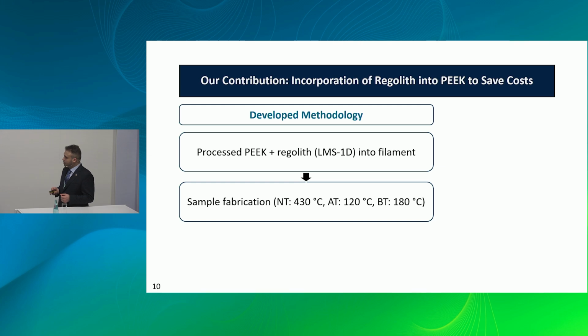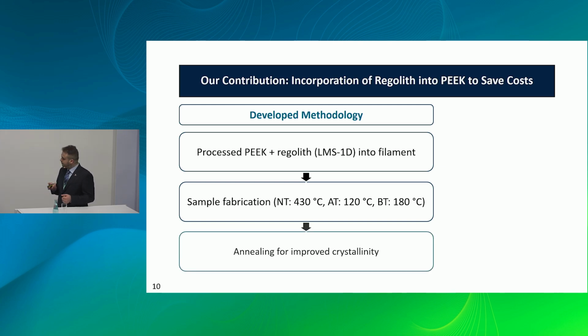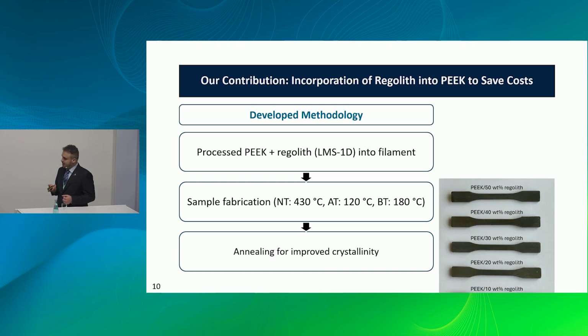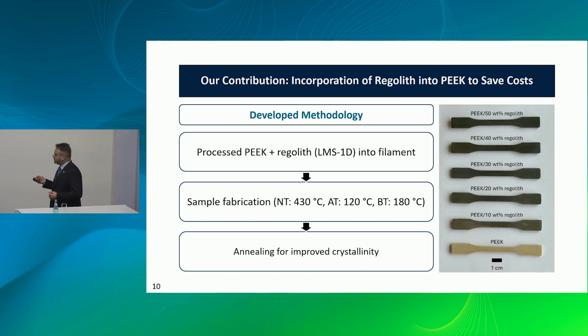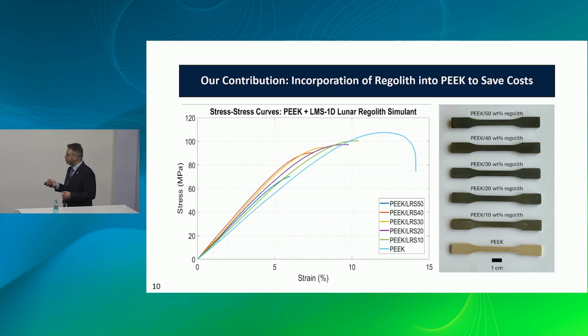The nozzle temperature is around 430 degrees. Ambient temperature is 120 degrees, and bed temperature is 180 degrees. We do simultaneous annealing during the process, and post-processing annealing is the next step. These are samples printed using PEEK and regolith, from pure PEEK to 50%. That is the maximum percentage of regolith that we achieved so far.